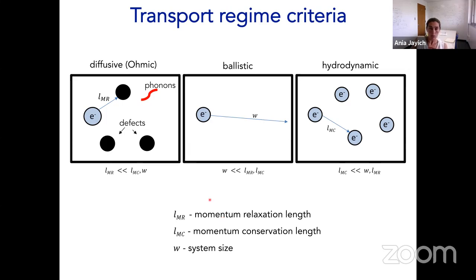In the ballistic regime, which is often observed at low temperatures and in clean materials, there are not a lot of defects, phonons have been largely frozen out, and electrons scatter off the walls of the device, which has a characteristic length scale of W. This ballistic regime is entered when the width of the device is smaller than both the momentum relaxing length and the momentum conserving length. Again, this happens at low temperatures and in clean devices.